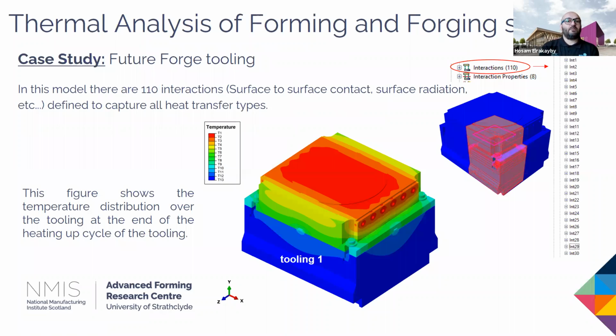So here you can see one of the tooling we are designing for the open mode forging. We focus on maintaining the top surface of the tooling at target temperature for forging, whereas this top surface will be in contact with the billet to be forged. At the same time, we want to reduce the temperature at the bottom of the tooling as much as possible, where the tooling will be assembled with the press bed. You can see on the top right that we used 110 interaction to reflect accurately what's happening in reality. This will make us predict accurately the temperature distribution over the tooling.